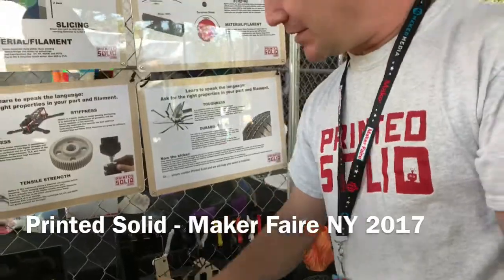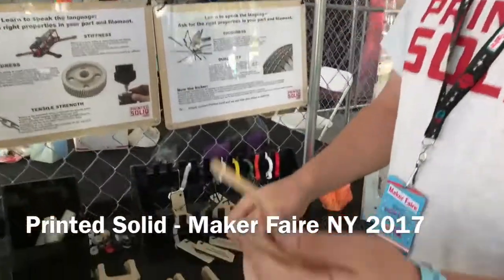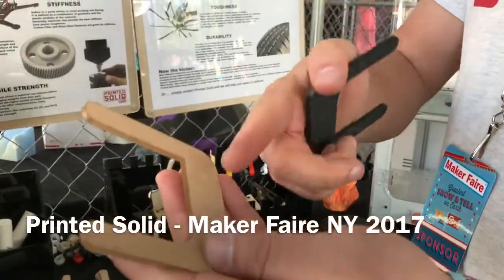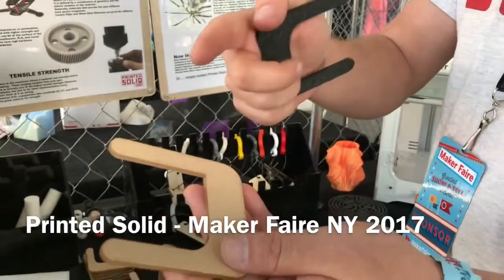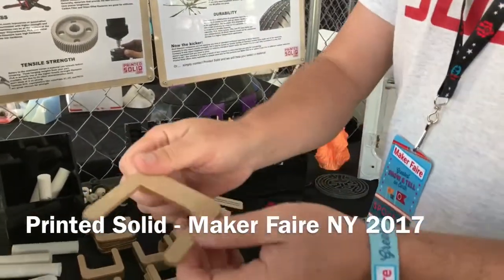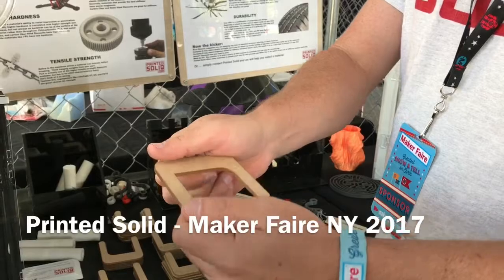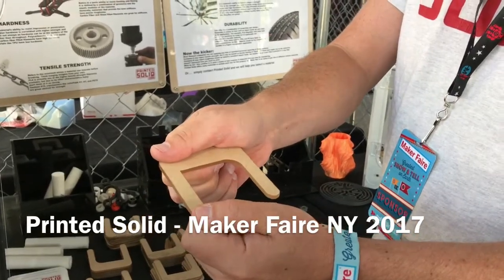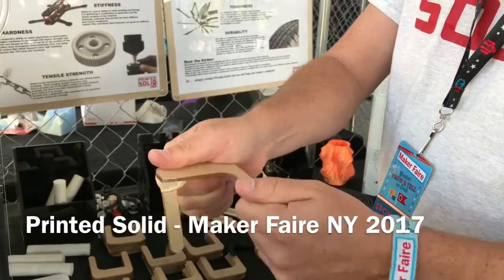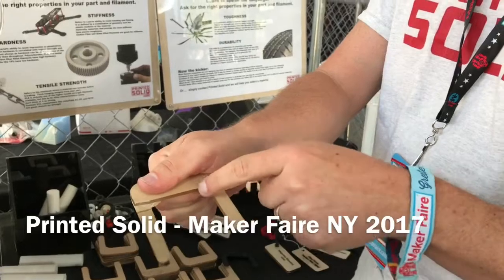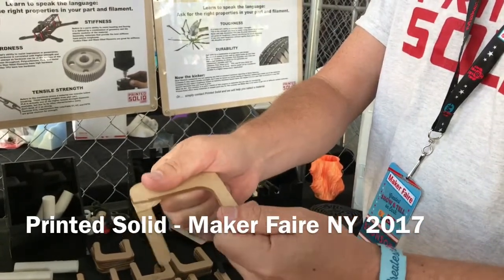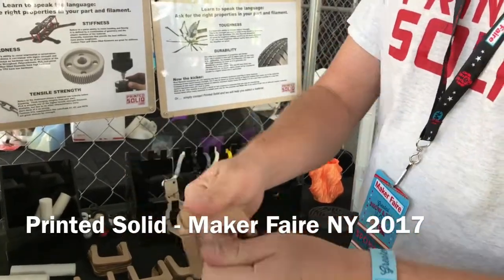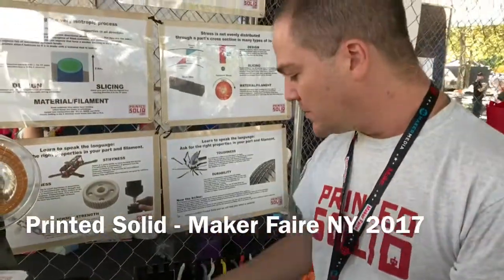Then we made these pieces to show the concept of stress concentration. In any material where you have a change in geometry, your stress increases. So this is acrylic, a relatively brittle material, so I can take it with a stress concentration piece and snap it just like that. Now I take it to the other corner where we put on a fillet to remove the stress concentration, and it's harder to break and the break point moves.